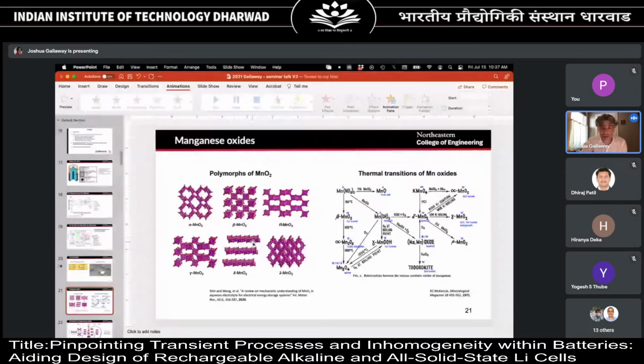And the reaction is actually somewhat complicated. This is a cartoon of the reaction. You begin with this material, take it through a formation cycle, and then it forms this layered material. These are the layers right here, and the ions go in and out of the layers. This is the cycling reaction. These yellow balls are the ions, and as you charge and discharge the battery, the ions go in and out of the layers.